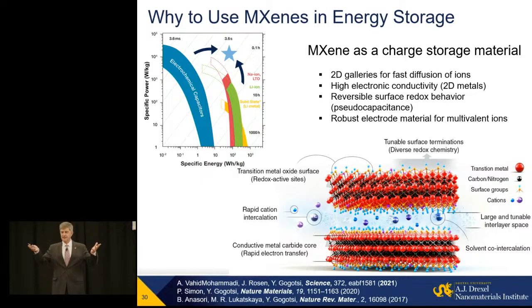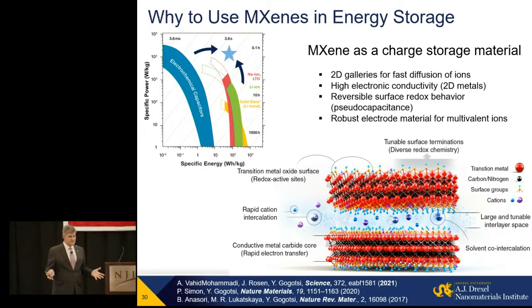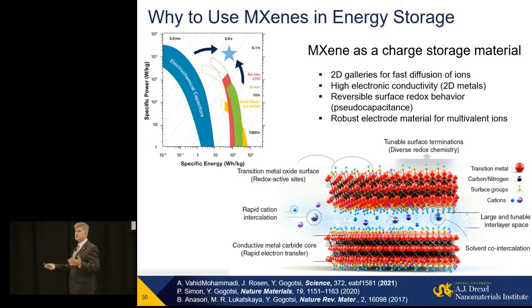Joule heating. It means that car batteries have expensive, complicated cooling systems, which make them bulkier and heavier. It also means that a lot of the energy that we produce goes to waste, heats the environment when you charge and discharge. Titanium carbide MXene has conductivity two orders of magnitude higher compared to porous carbons used in supercapacitors, the fastest energy storage devices. So if you combine all these properties, this may be a way to make very efficient fast charging energy storage. But there are many challenges.